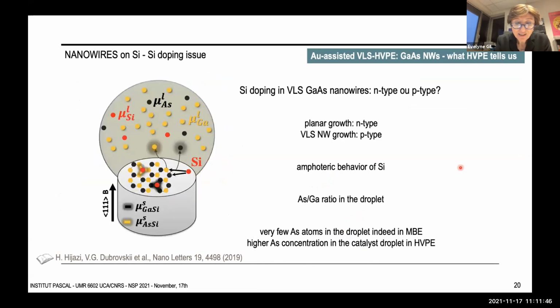Then what about silicon when it is introduced on purpose for n-doping? We know that it gives n-doping for planar growth, but it seems to give p-type doping for usual VLS and MBE growth of nanowires. So here again, HVPE helps in understanding the behavior because it brings to the table arsenic-rich catalyst droplets.